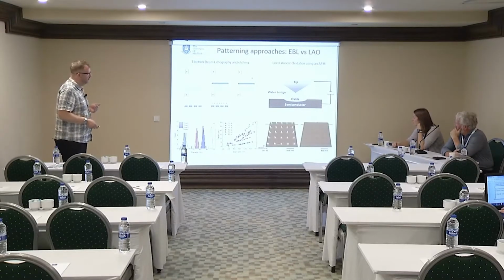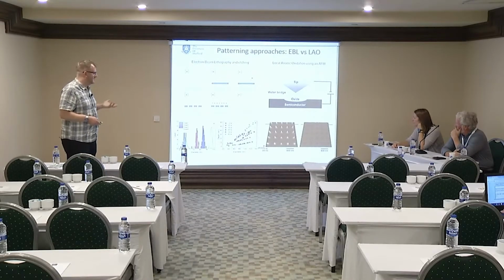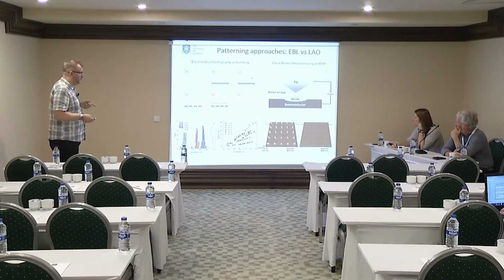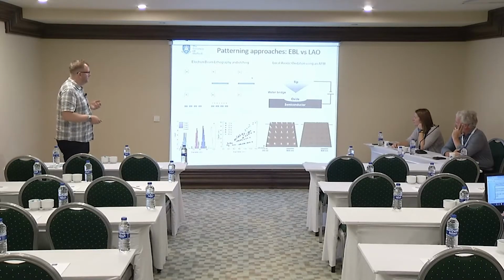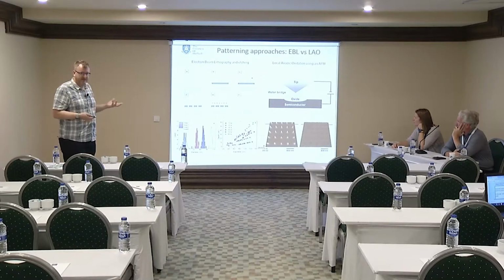So here we have an array of oxide mounds, and then we can wash those away with hydrochloric acid to leave us with an array of nanoholes. Also a serial approach, much slower than E-beam, but potentially, because we don't use resist, it might give us cleaner surfaces and better results.